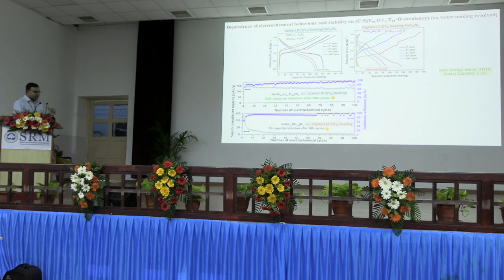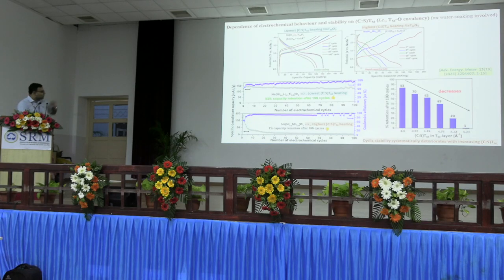Now coming to another thing which we observed, which we were not expecting: even when it comes to the electrochemical performance of these materials with varying charge to size ratio, even when nothing is exposed to air, synthesized and kept nicely in the glove box, absolutely well protected, still the ones with the low charge to size ratio performed better than the ones with the high charge to size ratio. This was not something which we were expecting. We were just investigating the electrochemical behavior because we had made the materials. But we made an interesting observation. As the charge to size ratio in the transition metal layer increases, we see the cyclic stability decreases drastically, and it follows a trend.